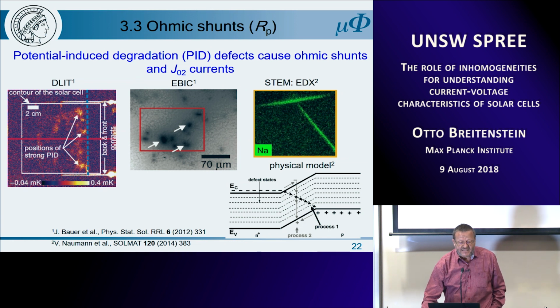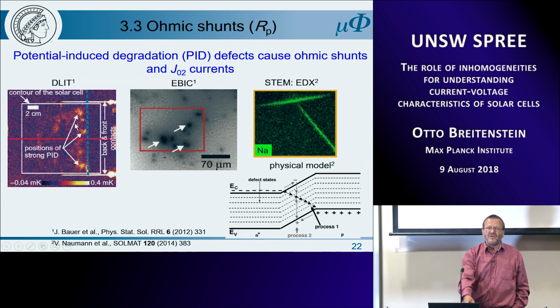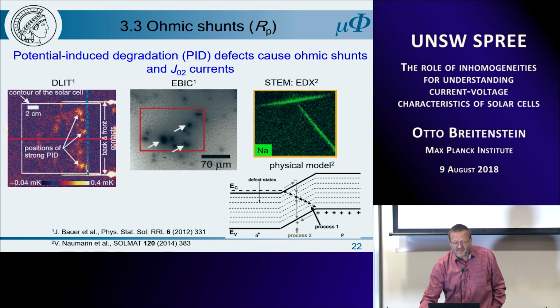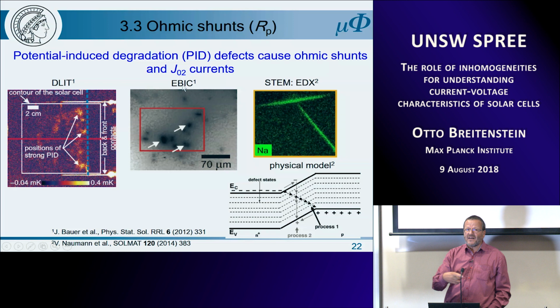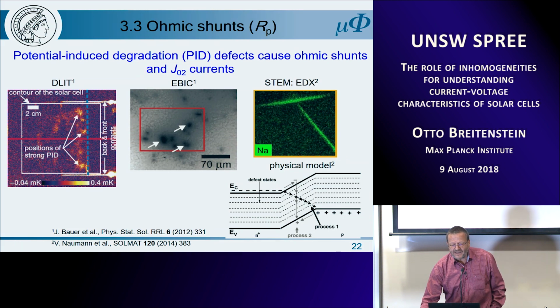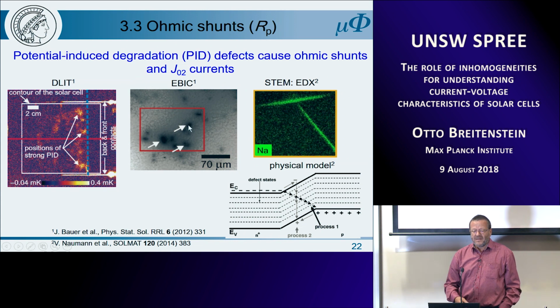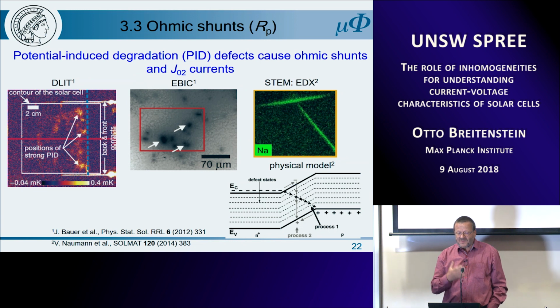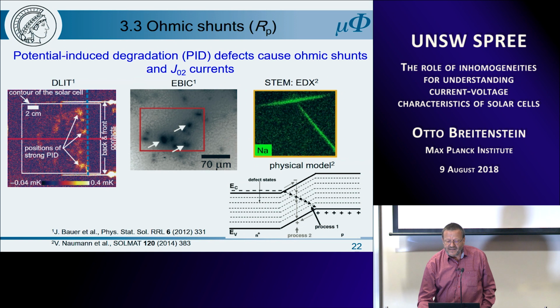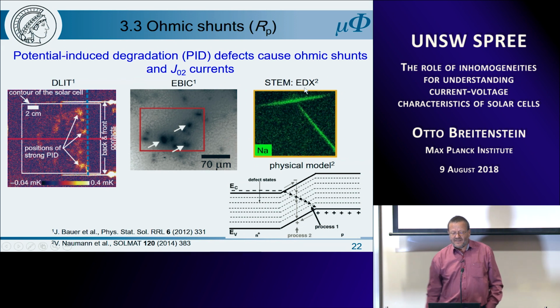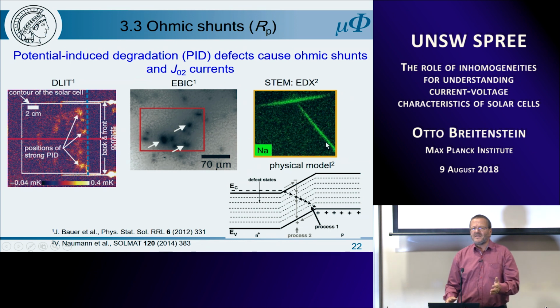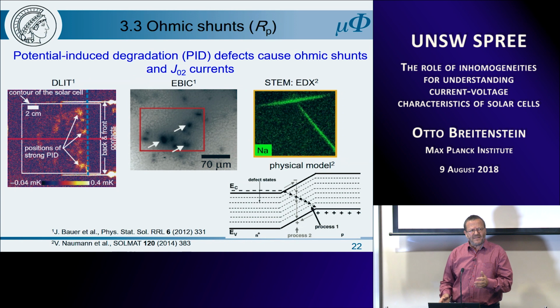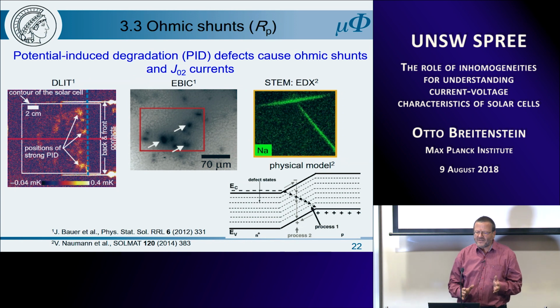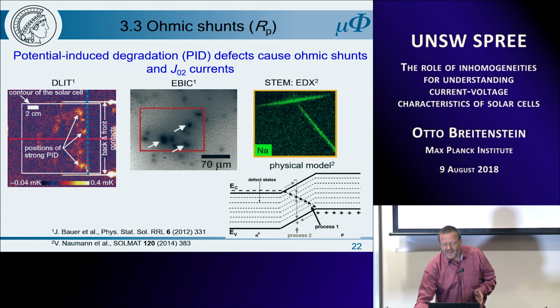And so we have seen these degraded cells, the positions of strong PID. It looks very cloudy in lock-in tomography, because lock-in tomography doesn't have a good spatial resolution. But if we look with EBIC, then we have this current distribution contrast, which I have explained at the beginning, and we see these dark spots. In these positions, some TEM specimens have been prepared, and very high resolution energy dispersive X-ray measurements have been performed, and this is the sodium signal. It turns out that these defects are planar defects lying on 111 planes like stacking faults, but they are not simple stacking faults. They are planar defects heavily coated with sodium, and this is proven here.